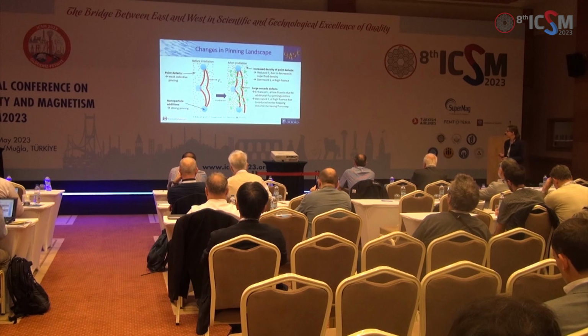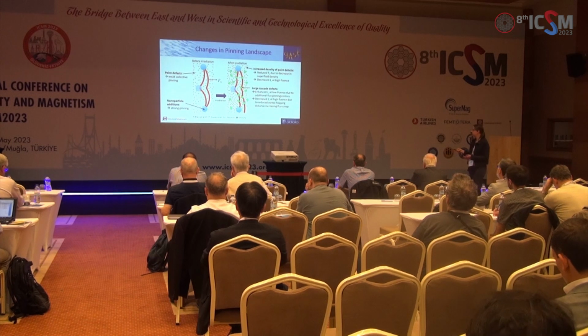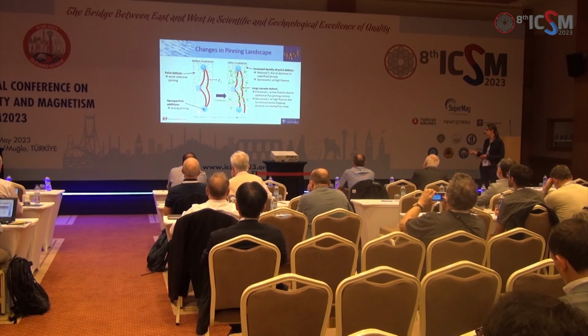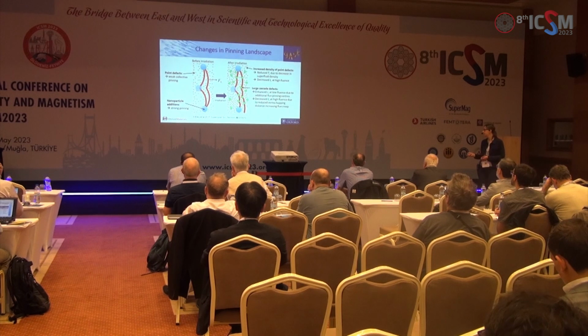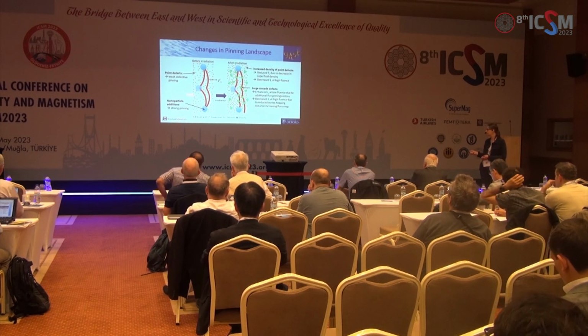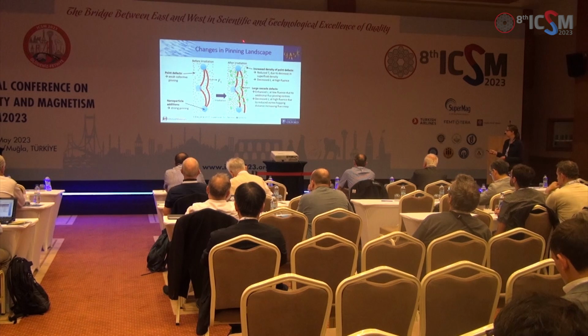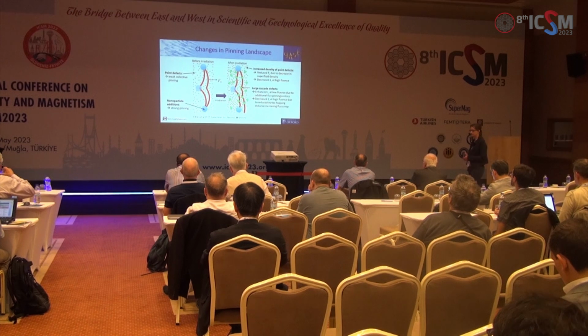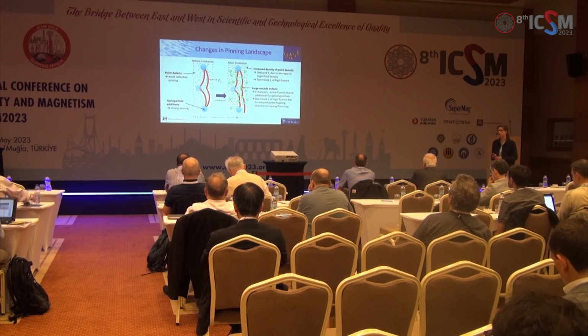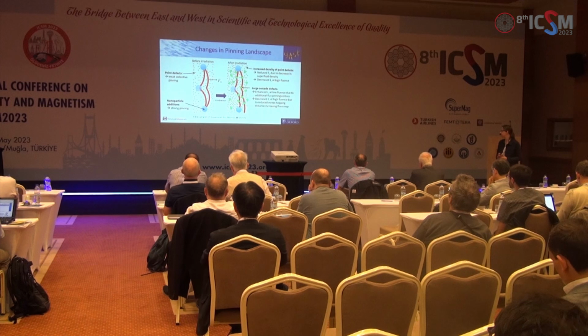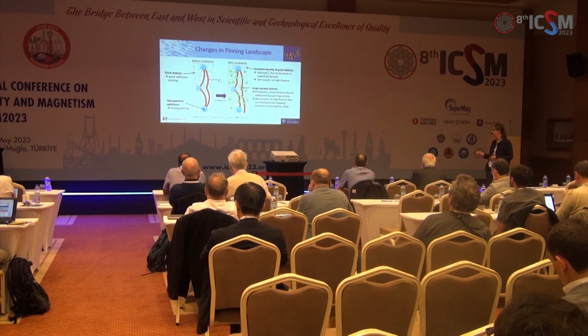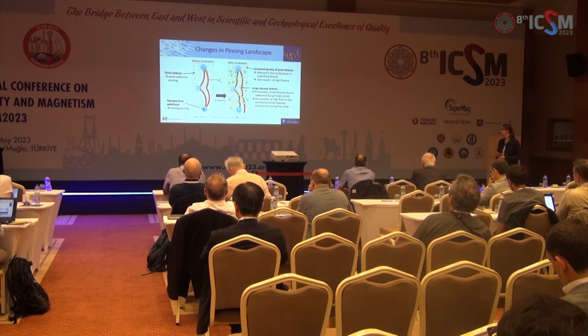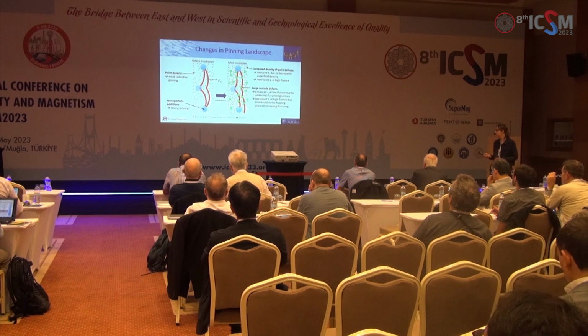So here's just a schematic to explain what's happening when we do this irradiation. You'll see that before irradiation we might have some strong pinning defects already there in the material. We've probably got lots of point defects that do this weak collective pinning. When we irradiate it, we produce these damage cascades, these things here. They'll produce additional flux pinning centres at low fluence, but at higher fluence you might end up with increased flux creep, which will decrease JC. The point defects also increase in the matrix. We get more point defects in here, which reduces TC and will eventually reduce JC at high fluence as well.